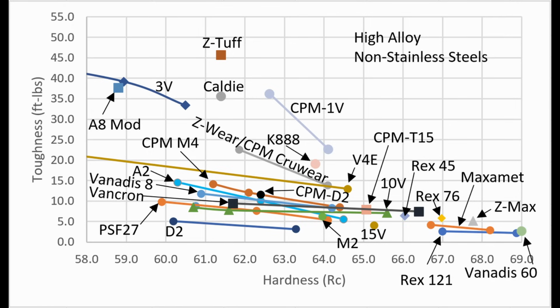Rockwell CPM1V. That is a non-stainless steel with very low carbide content, very high toughness, relatively low wear resistance, or maybe medium low wear resistance. And so that steel is pretty good. So would I make a better one than that? I'm not sure. Now it can also go to lower hardness, and also you can see Z-Tuff on here has 61.5 Rockwell with higher toughness.